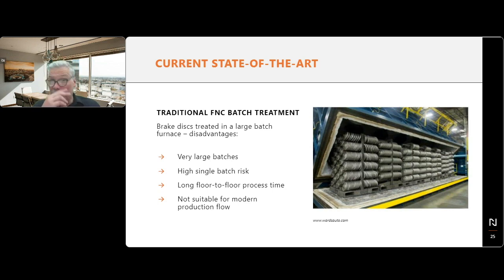So what you see first is a tip-up furnace, which was the type of furnace used since the very beginning of FNC treatments for brake rotors in North America. I believe the first trials ever for those treatments were done in a similar setting. So it has several advantages, obviously, and some drawbacks. As you can see, the volume of the furnace, which is huge, allows for the treatment of very large quantities of rotors. Hopefully, if the process succeeds, you have very good results. Obviously, there is also a risk associated with problems during the process, so you may eventually lose part of that load. However, the big advantage is productivity rates.